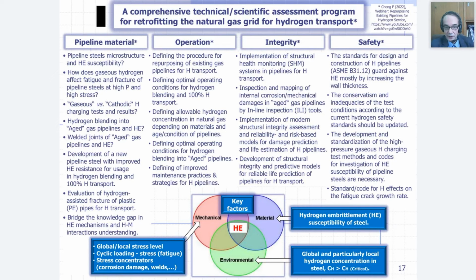Just briefly, pipeline material points. It's necessary to investigate and correlate pipeline microstructure, old steels, new steels, and hydrogen susceptibility. To investigate further the effects of fatigue on the fracture of pipelines, particularly at high pressure and high stresses. Also, we have numerous cathodic hydrogen charging results, but actually, when we talk about pipelines, we need a gaseous source of hydrogen in order to reveal the true hydrogen embrittlement susceptibility. So these 2 types of results from cathodic charging or gaseous charging are not comparable.